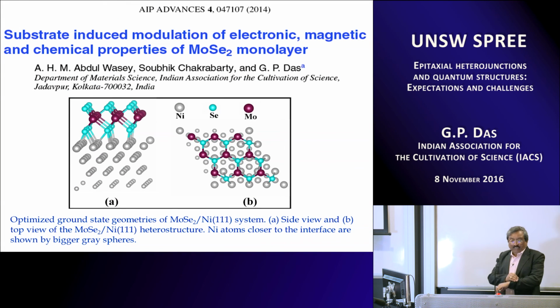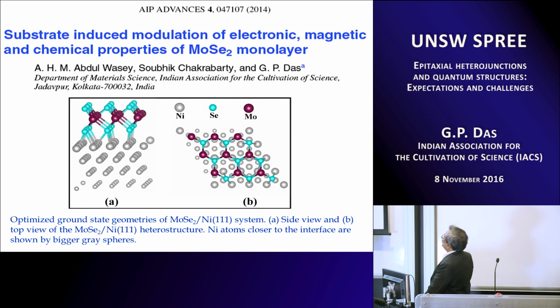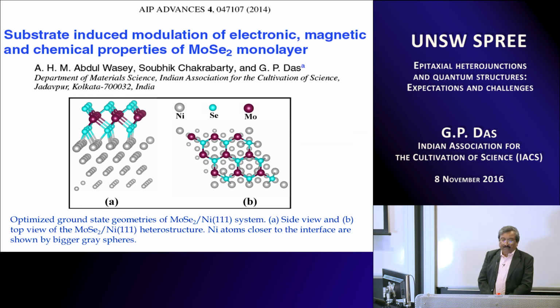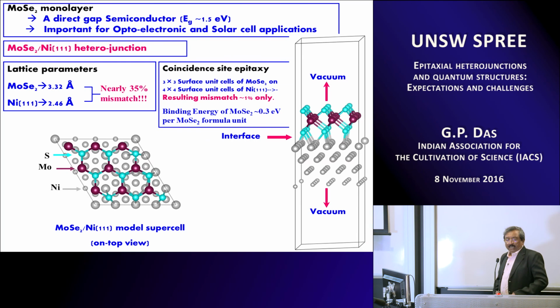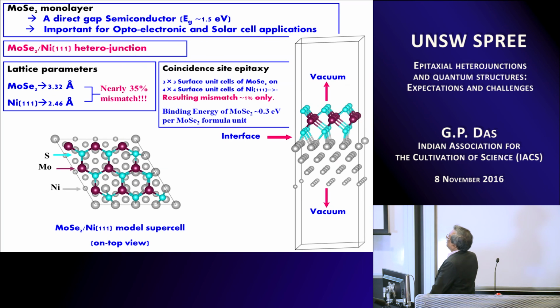Yeah. So for the last 1 or 2 minutes, I will give you an example of how in a layered transition metal dichalcogenide like MoS2, MoSe2, molybdenum diselenide, how the electronic, magnetic as well as the chemical properties of the MoSe2 monolayer get modulated because of the existence of a substrate. So it is a substrate induced modulation of electronic, magnetic and chemical properties. Now MoSe2 monolayer is a direct gap semiconductor with a band gap of about 1.5 electron volt, and it is important for optoelectronic and solar applications.